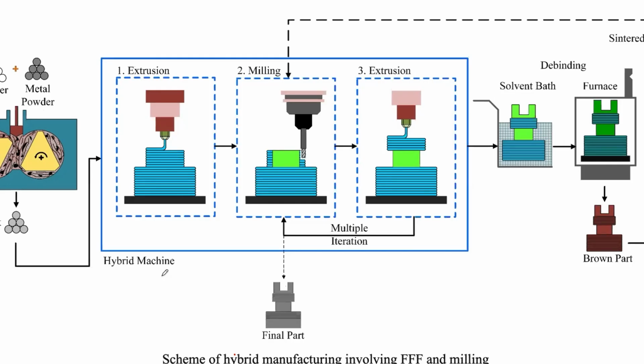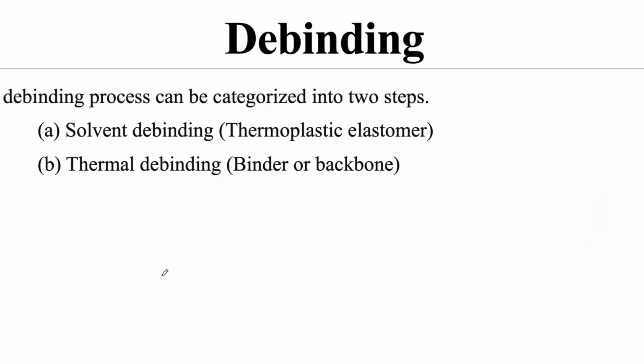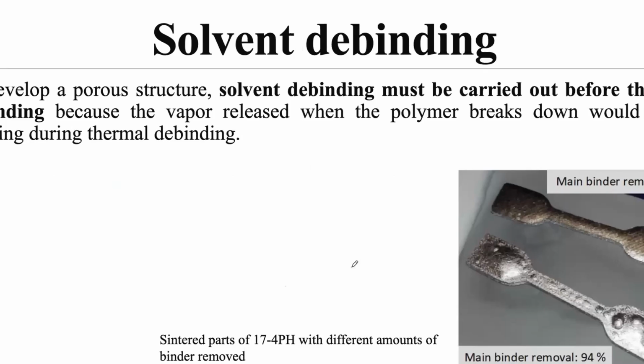Yes. So coming back to the topic, once you have done this, then you put it into the debinding. You might ask, sir, what is the need of debinding it in a solvent? We can put everything directly into the furnace. The sintering cycle can evaporate everything, and then the metal powder will join. That is also possible, but that will create some problems. If the binder is not removed completely, what will happen? You will see blisters like this. The reason is because you have not done a proper solvent debinding.